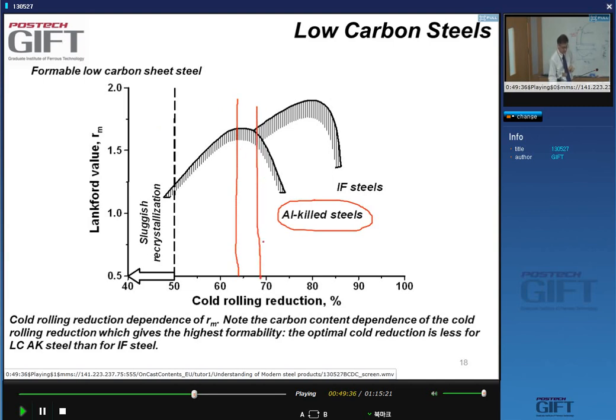This is okay. 70%. Because here we have a maximum reduction. The lower amount of 50% is related to the fact that if you don't deform enough, the recrystallization will be very slow, right? So you need to deform at least 50% reduction. Otherwise, the recrystallization will be incomplete. The maximum reduction is around 70%, because if I go beyond that, I get the texture developing in the wrong way, and I get a reduction in deformability. So you only have a reduction window of 50 to 70% if you use a low-carbon steel.